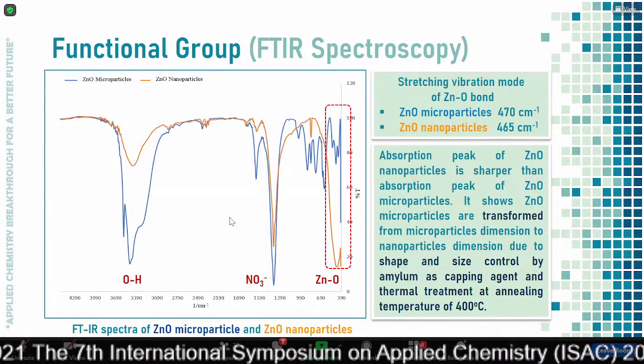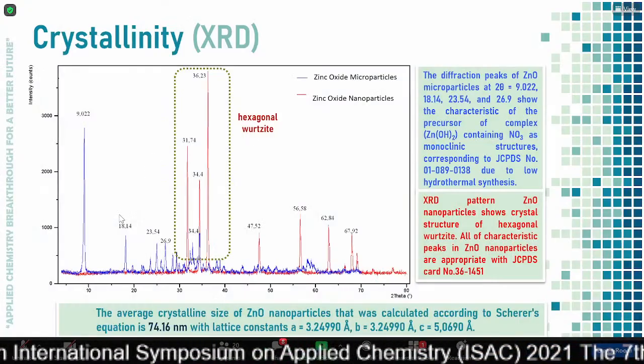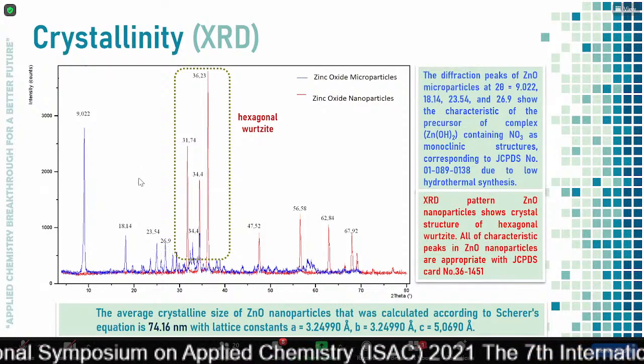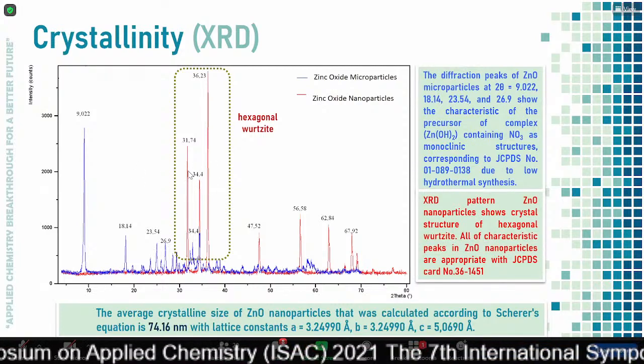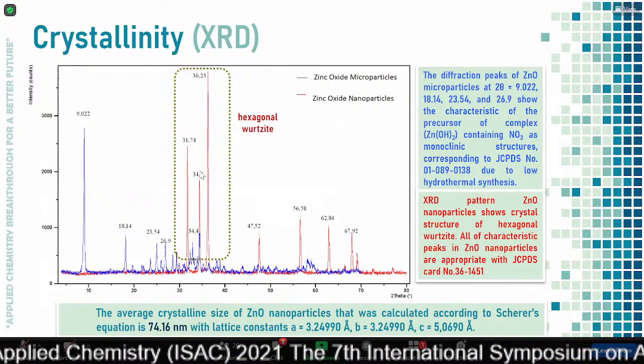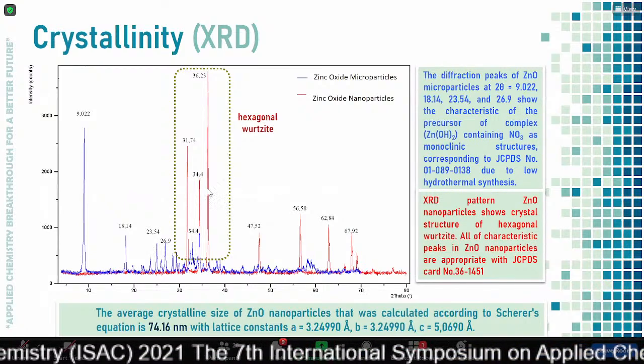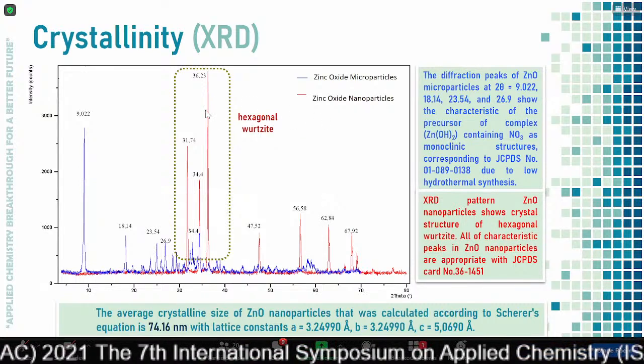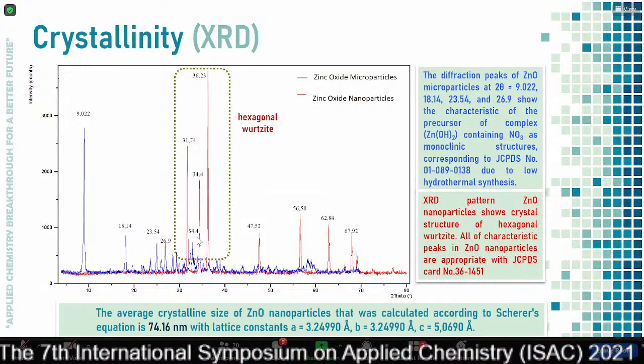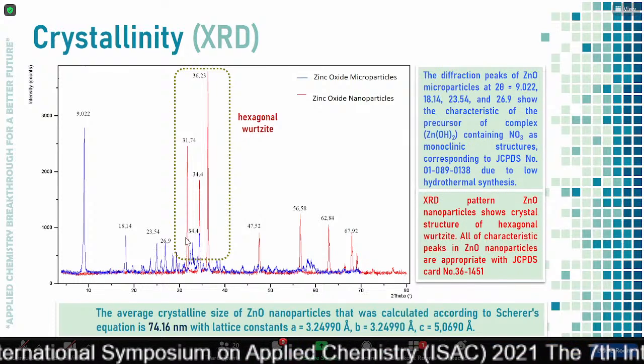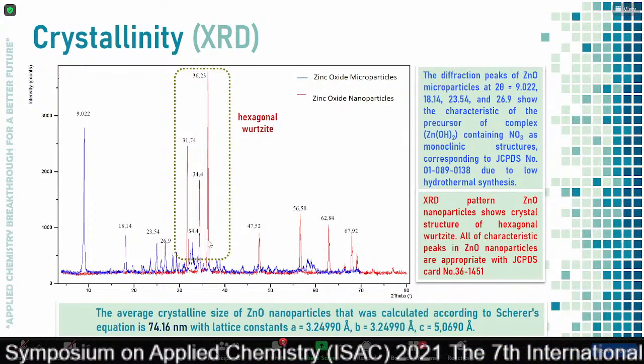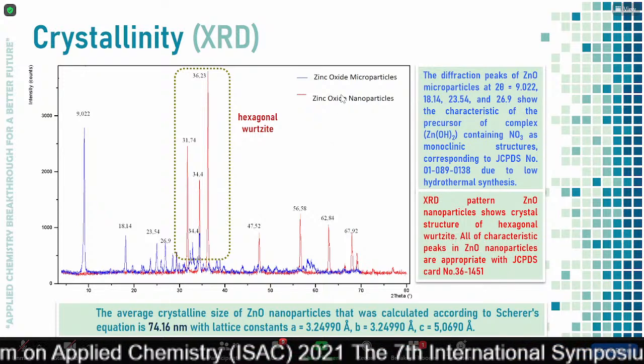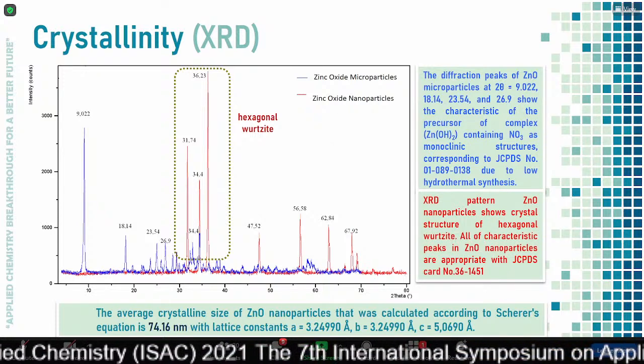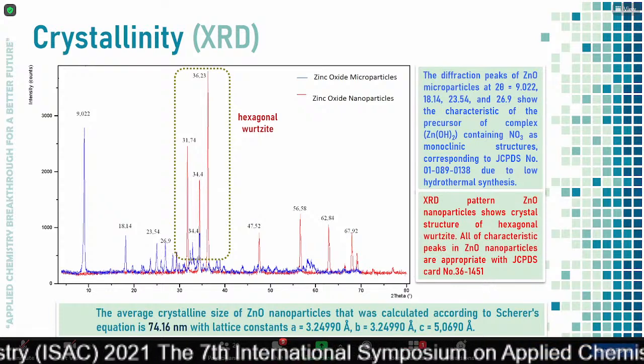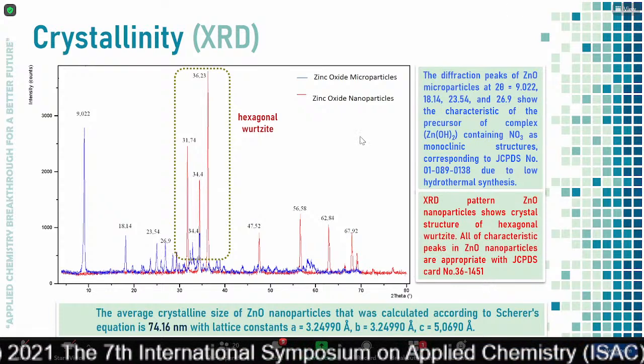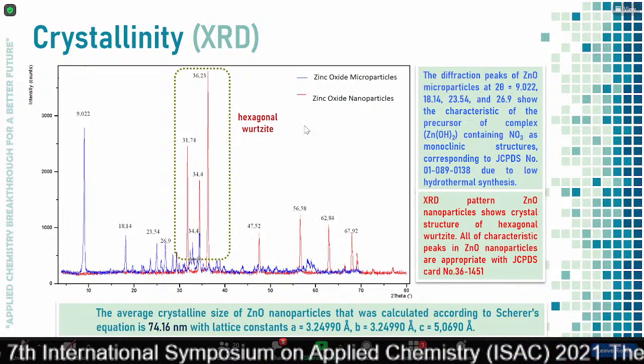And if you look at the XRD here, it's quite clear that this is the zinc oxide nanoparticle, the red one. The hexagonal phase is quite clear here, and the crystallinity is also quite high. Only a small amount of zinc oxide here belongs to zinc oxide microparticles. So again, there's no direct relationship with the particle size, but only the composition. I think that's my answer for Dr.